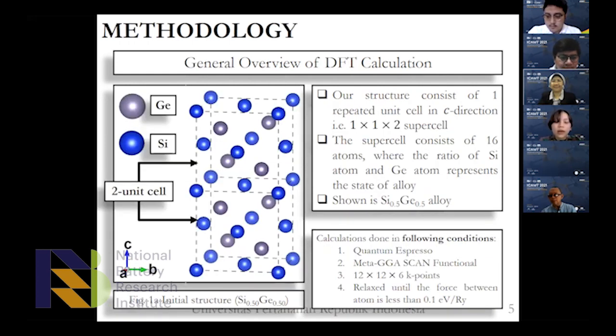Well, as you can see, the figure on the left shows our initial configuration of silicon germanium alloys with the same composition between silicon and germanium atoms. The dashed line shows the unit structure that is repeated in the C direction to produce a 1 by 1 by 2 supercell structure. And this image on the left is silicon 0.5 and germanium 0.5.